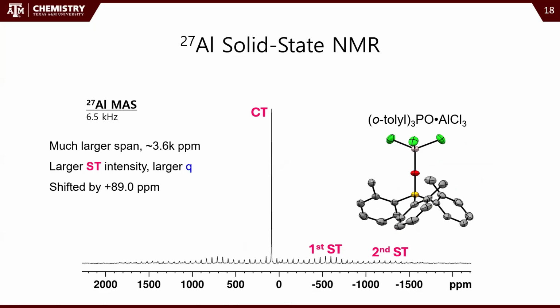If we move on to our adducts, then you can see we get even broader. So now we're over 3,000 ppm, and it's pretty impressive. There's a lot of manual baseline correction. Spectrometer doesn't like to play nicely when your sweep width is 4,000 ppm. So these were a little bit of work to get. But you can see that we have a central transition there, and then our first satellite transition, and then our second satellite transition is kind of over here.